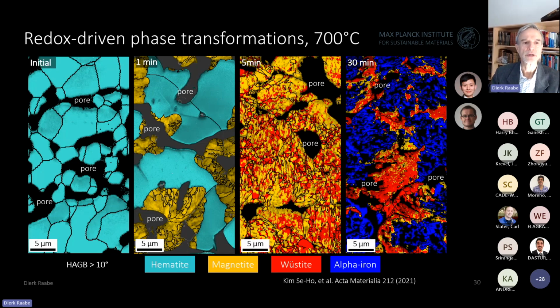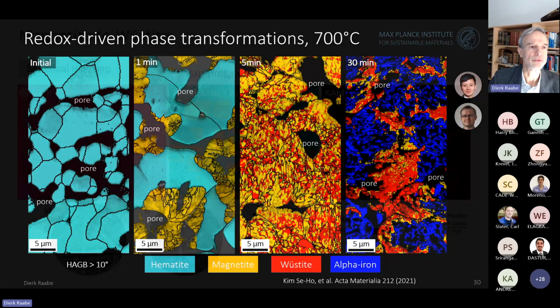And that means we seem to encounter here certain reshuffling, relaxation of the iron as the oxygen gets depleted and the structure gets more elastically stressed. But this is still under scrutiny, and we intensely investigate how this exactly works, this interesting, say, decomposition type of phase transition. And at the end, you see then how the alpha iron in this already very, very porous, more than 45% porous structure is evolving from the wüstite.